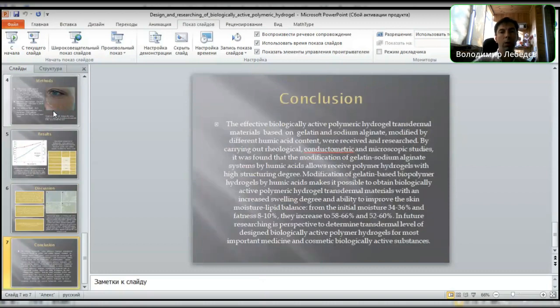So we can make the following conclusions of our research. Effective biological active polymeric hydrogel transdermal materials based on gelatin and sodium alginate modified by different humic acid content were received. Modification by humic acid makes it possible to obtain polymeric hydrogel transdermal material with increased swelling degree and ability to improve the skin moisture-lipid balance.